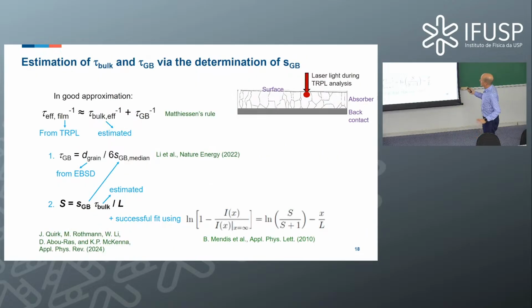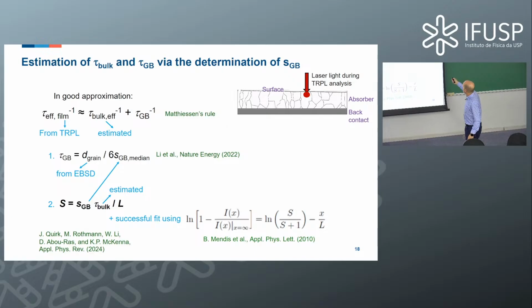To be a little bit more precise, the bulk lifetime can be measured by means of photoluminescence, but time-resolved photoluminescence. So we look at the transient, basically, how strongly the intensity decreases with time, right? This is one of the established ways to determine the lifetime. And we can then basically approximate this effective lifetime that we measure here as the inverse, the sum of the inverses of the bulk lifetime and the grain boundary lifetime. So this actually is quite elegant because it gives us also an estimated value for the bulk lifetime, which is normally not so easy to determine.